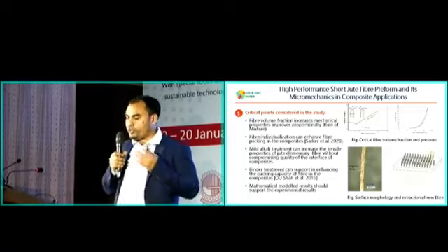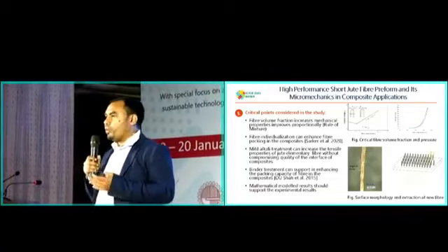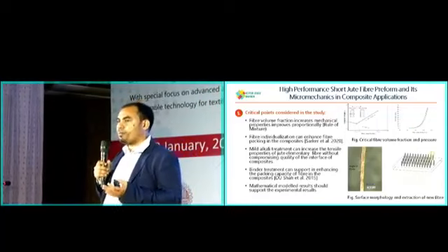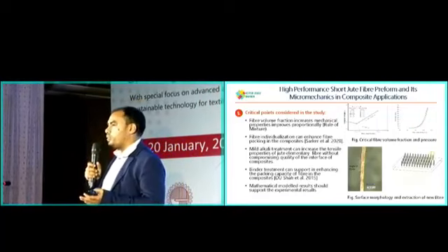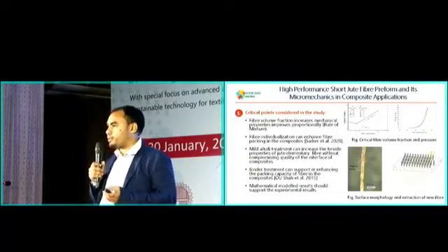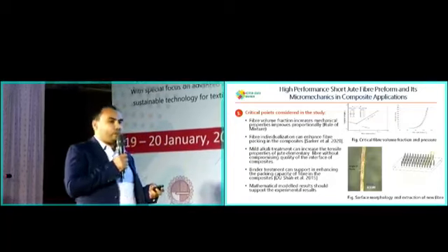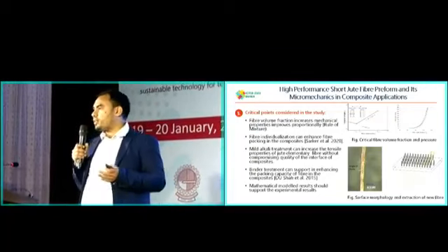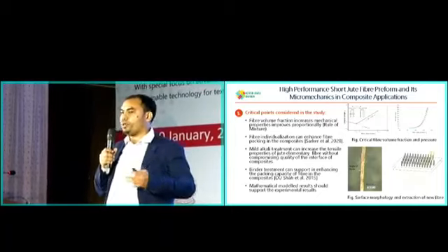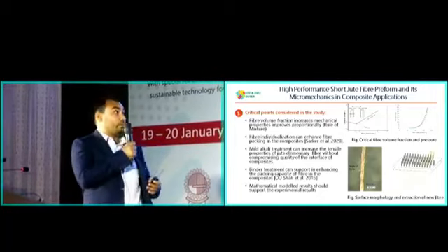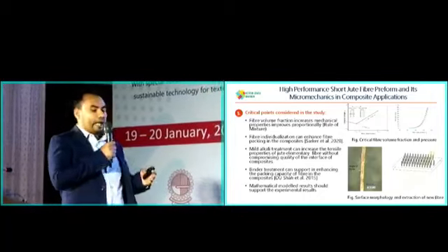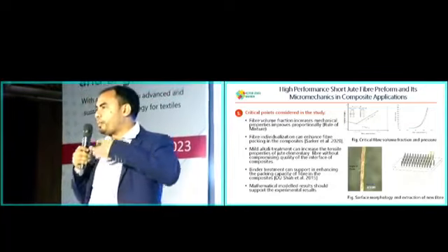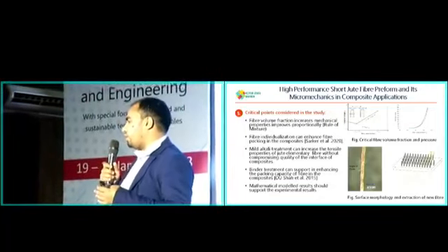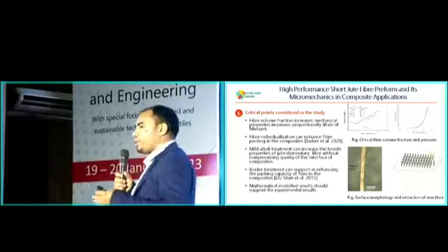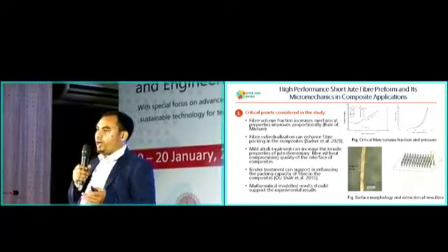In the infusion process and also the compaction process, you cannot think of achieving a fiber volume fraction of more than 30% or 40% for these fibers. But if you want to get maximum mechanical properties, then you have to achieve the maximum fiber content in the composite materials. And another point is applying pressure. If you apply pressure to increase the content of the composites, then you can damage the fiber and also reduce the mechanical properties.